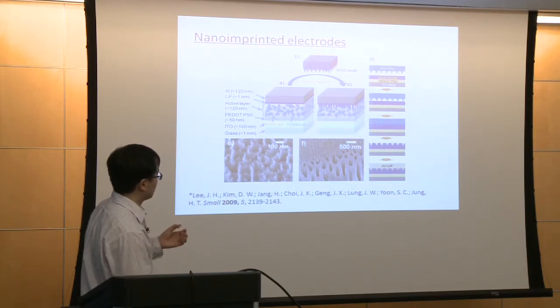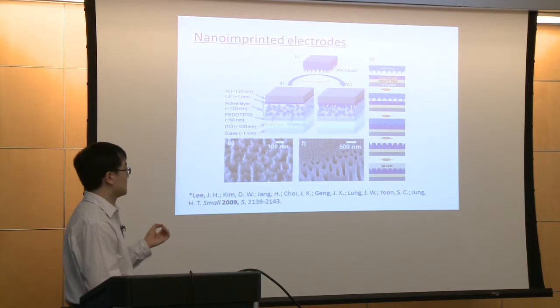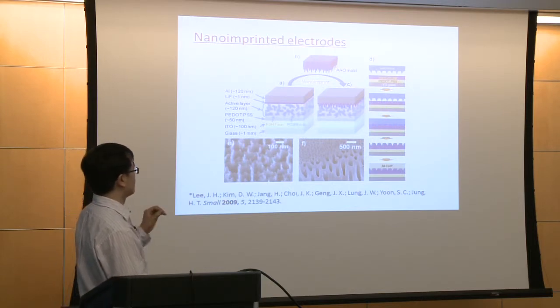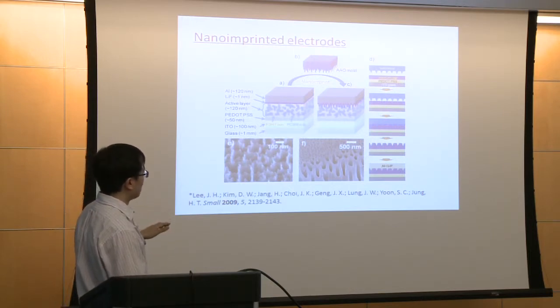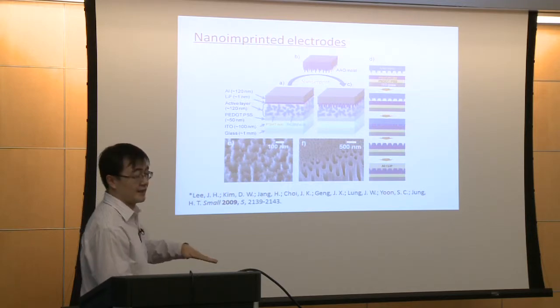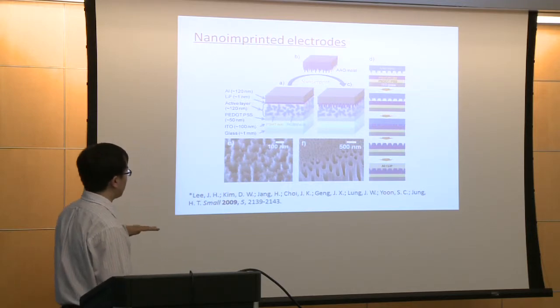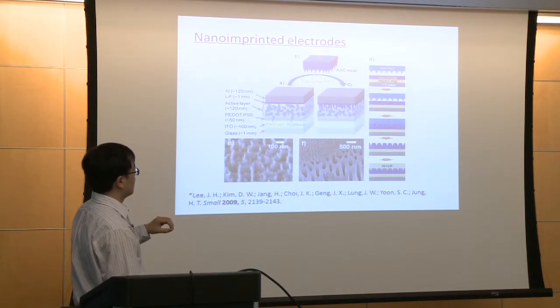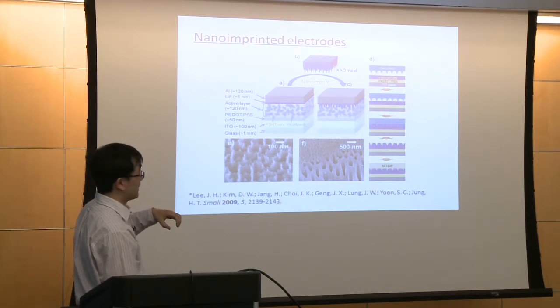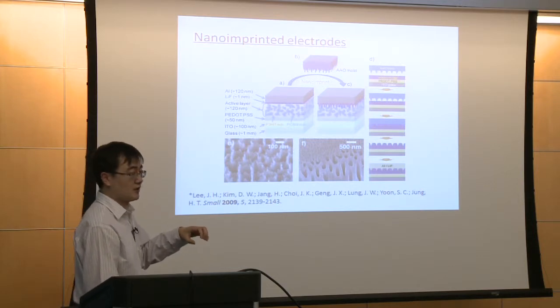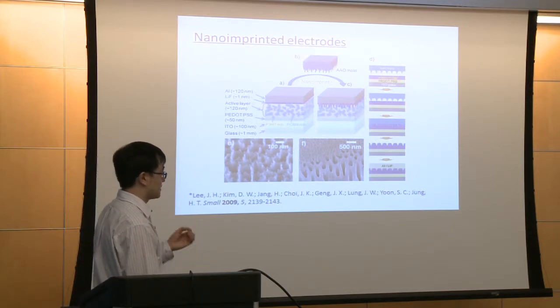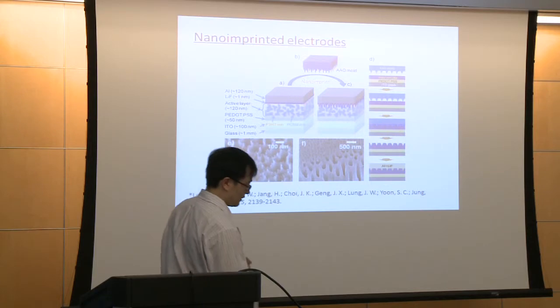However, first of all, it's very time costly. It takes a very long time to design the AAO mold and to put that mold into the active layer. That's one problem. The other problem is the length of the electrodes inserted into the active layer is very limited, which means the efficiency enhancement is also limited by this method.